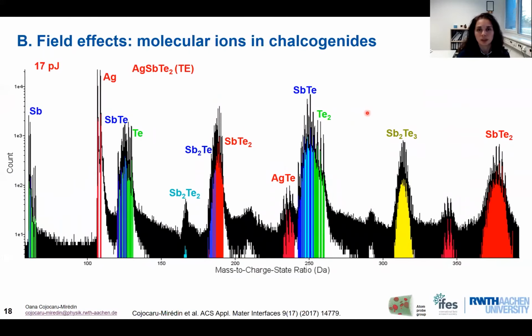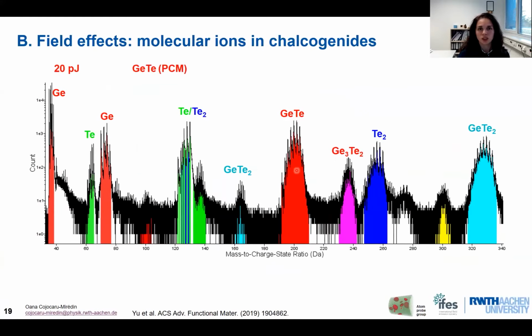Now, if we take the silver antimony telluride, this is a thermoelectric material. It contains antimony, and we can suspect, of course, that it also has a very high proportion of molecular ions. And we see here nicely that we have all possible statistical molecular ions that can be formed, like antimony telluride, antimony-2 tellurium, antimony-2 tellurium-2, and so on. If we calculate the fraction of molecular ions present in this material, we have about 63% of the total ions. So we have a very high probability to field evaporate not single ions, but molecular ions for this material.